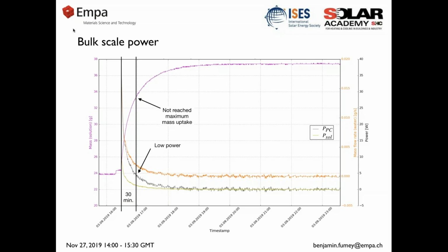And after 30 minutes, we have only about 5 watts, but we have not reached the equilibrium state of our sodium hydroxide. In other words, this points to the fact that for heat storage, where it is very important to be close to the equilibrium line to reach high energy density, we're going to have a heat and mass exchanger that is not power optimized, but needs to take into account the low power in the process of moving towards an equilibrium state of the concentration of the sorbent to the vapor pressure.